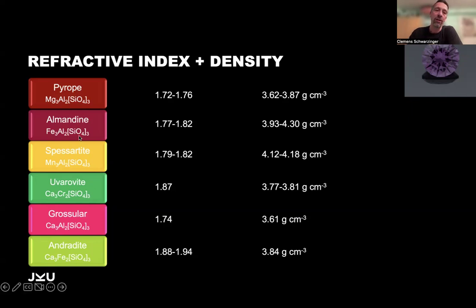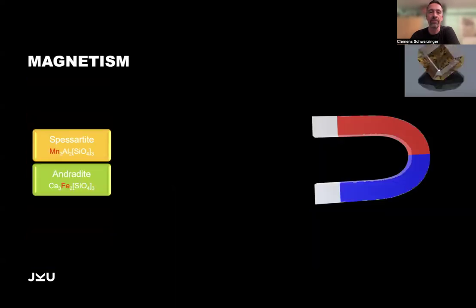They fall under the linear mixing rule. So if I have a mixture of pyrope and almandine, I can calculate from the measured density. But you never know if anything else is in between. And if you have ternary and quaternary mixtures, all your mixing rules cannot be applied and you just get random numbers. So it's nice to get a first idea about the composition, but you cannot do a definite check with refractive index and also not with the density.